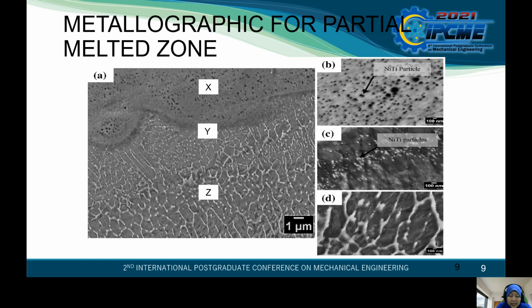Basically, 3 regions were produced in subsurface material after cladding process. First, clad layer. Second, heat affected zone or partially melt zone. And the third layer is substrate. 3 region formation in clad layer was due to beam interaction time and laser power. For example, figure A shows presence of NiTi particle in clad layer was due to incomplete melting of the nickel titanium particle within the rapid residence time. In the upper region, X and Y of figure B, incomplete melting of nickel and titanium particle was due to different melting point of nickel, titanium and steel substrate.